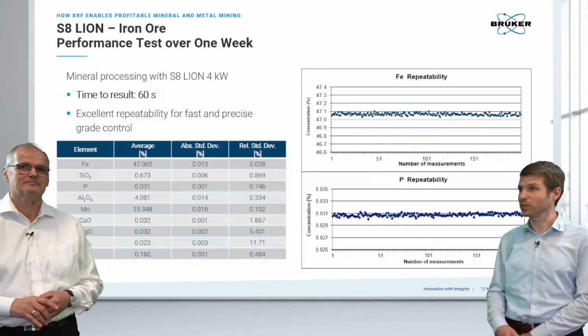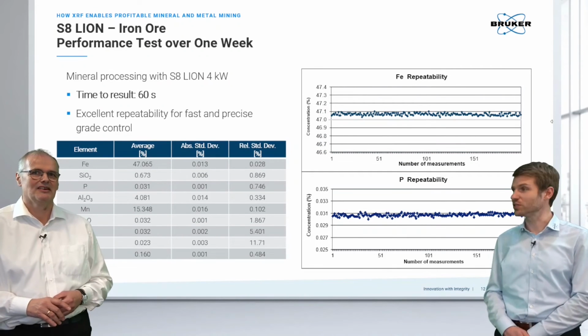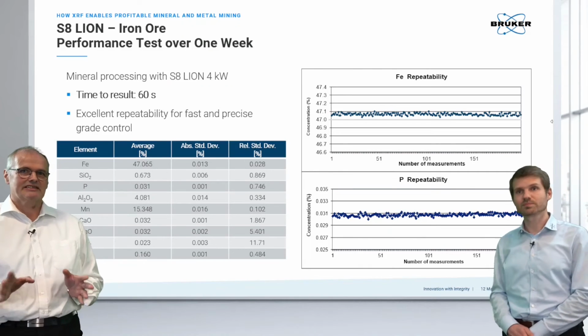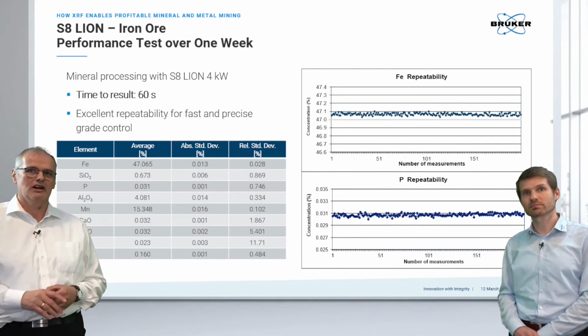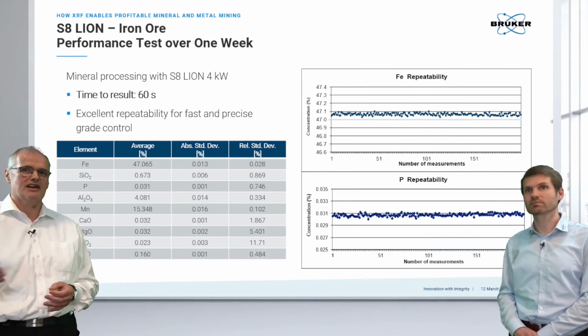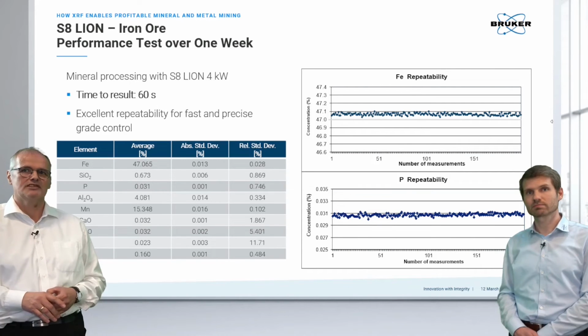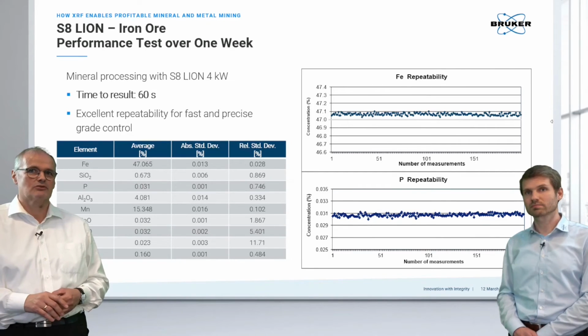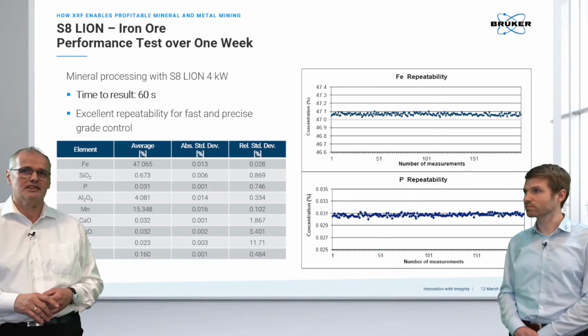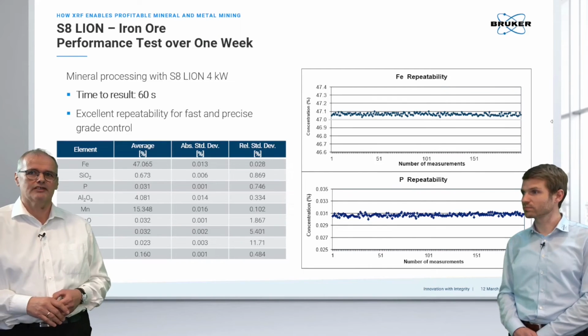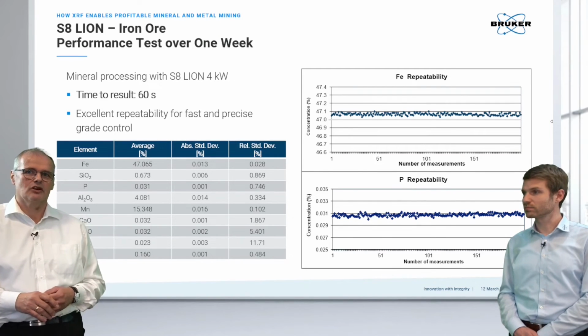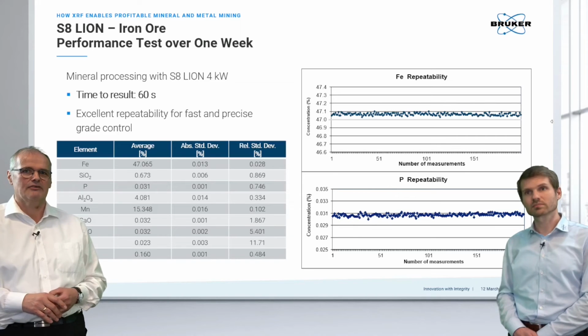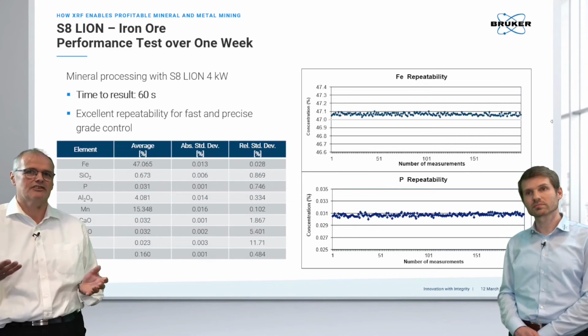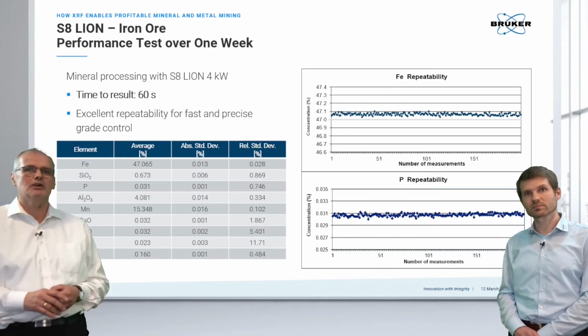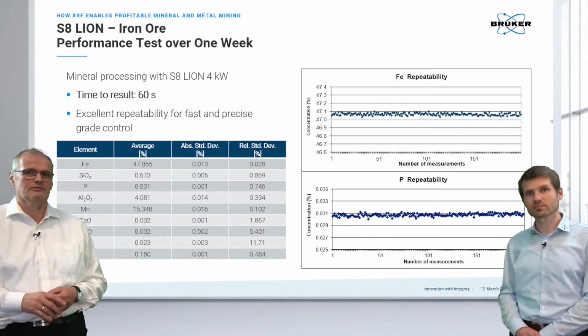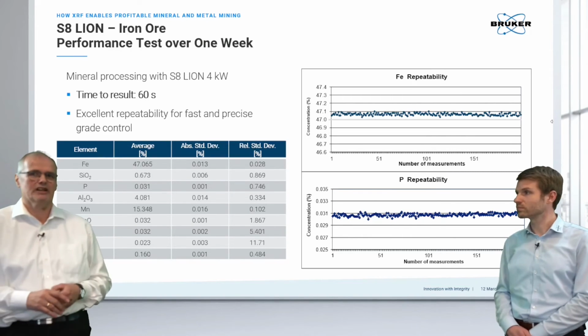But for that, I guess you need a really extraordinary precision and stability, don't you? Exactly. Taking into account that there is no moving part, we just move the sample in, we have fixed channels. We see that the iron repeatability is great, even below 0.1%. And also looking at an important penalty element like phosphorus or silicon, we are at a level of 300 ppm. We are at a relative standard deviation of about 0.2%, which means it's world record, right?